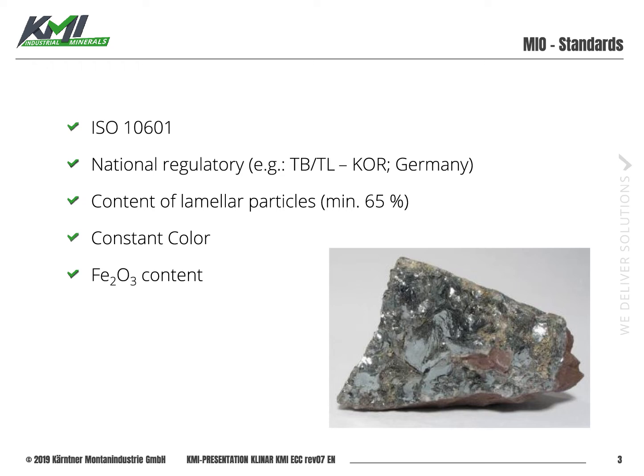The most important quality criterion of micaceous iron oxide is the content of lamellar particles, which has to be minimum 65% according to the ISO standard. Then you need a constant color, which should be gray with a metallic sheen. And also the Fe2O3 content is defined with a minimum of 85%.